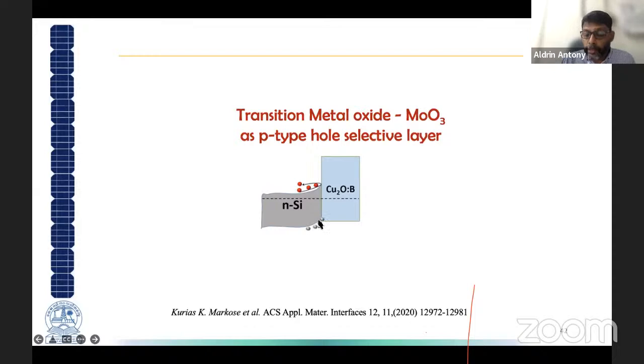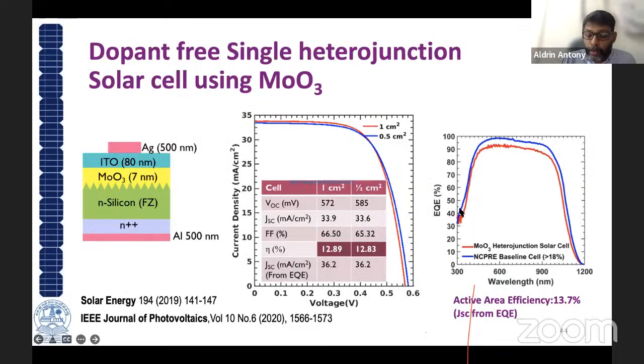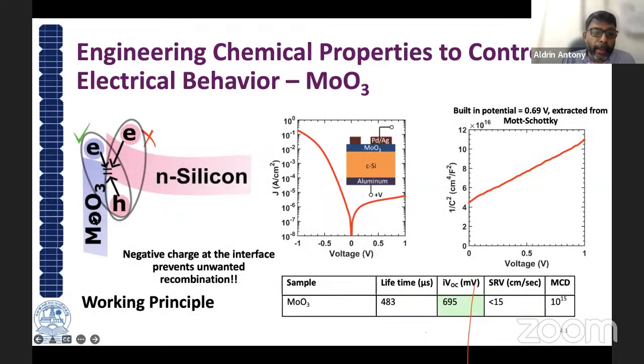And so this is what you could see here. MoO3 is like this, and when it comes in contact with the silicon, the band bends in the upward direction, and there will be a lot of trap levels in between this MoO3 and silicon, which helps all the holes to accumulate here, and then it will pass through these defect level states and get a thermionic emission or tunnel to the other metallic contact here.